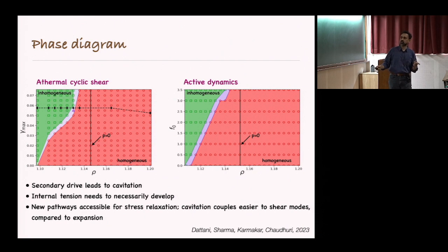The important statement here is that you need internal tension or pressure needs to be negative for this cavitation process to happen. In the pressure positive zone, even with mixing of these various modes, cavitation is not possible. What we essentially see is that new pathways become accessible for stress relaxation, and cavitation couples easier to the shear modes at these densities.